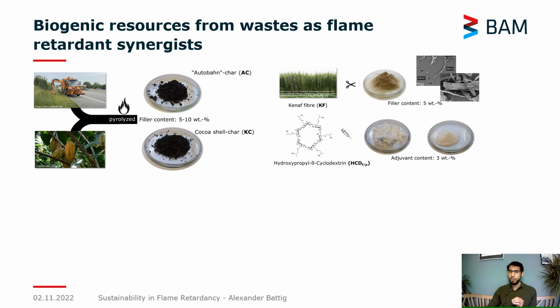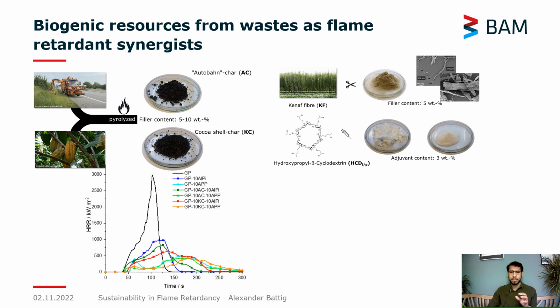And some interesting things happened here. What we saw was that by using our different types of fillers, you see a reduction of the heat release rate with respect to time compared to an unfilled material. So the black line, what I'm showing you here is the heat release rate as a function of time. The black curve is the pure green epoxy resin, and the blue lines are just flame retardant compounds, and the red lines are combinations of our biochar and our